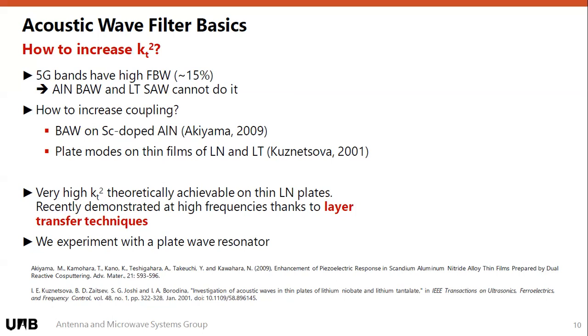It's using plate modes with thin films of both lithium niobate and lithium tantalate. This was originally just studied as a mathematical or theoretical study because there was no way in which you could get thin films of these materials with a correct crystalline orientation. With SmartCut technologies, now Soitec is selling a lot of lithium tantalate wafers, thin films of them. You can get really thin layers of lithium niobate and lithium tantalate on wafers mounted on top of a thin silicon oxide layer. So you can actually start playing with these modes.